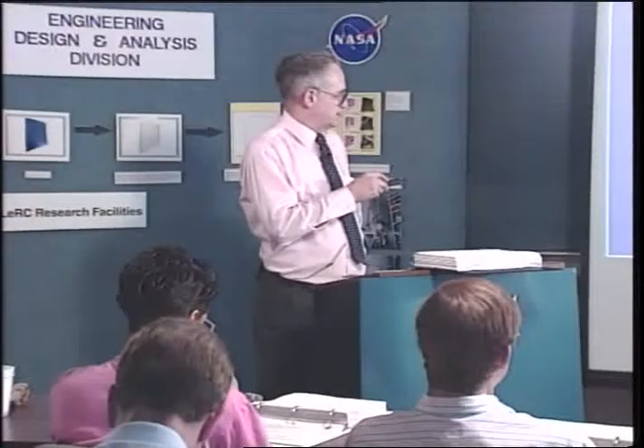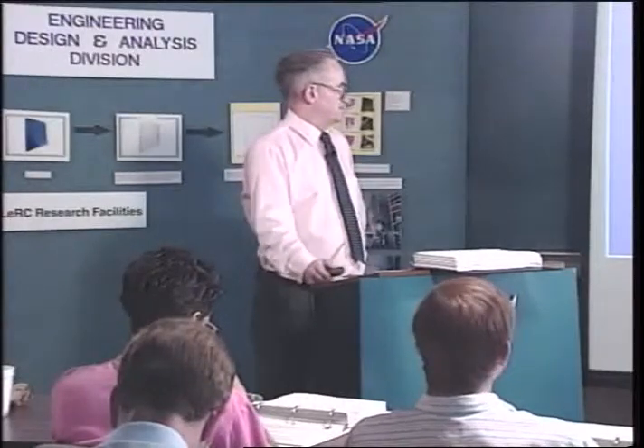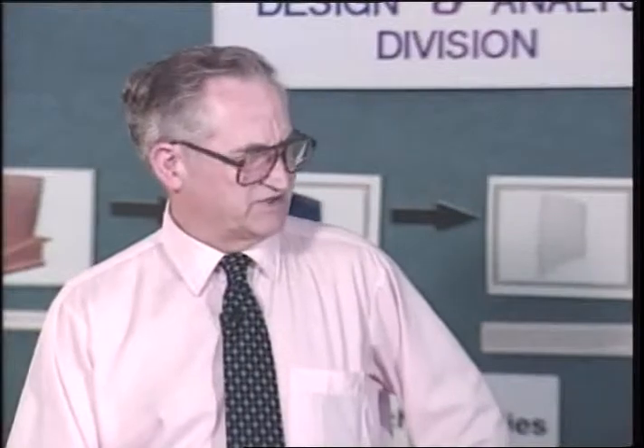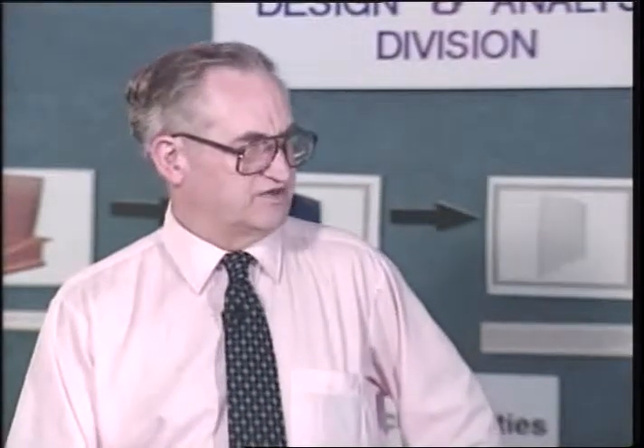Tool marks, nicks, and gouges are permitted on the under-head surface, but notice the restriction: as long as your micro-inch surface roughness does not go under 125. A 125 is really not too rough - it's a rough machining surface. The other place you would look at: if the head is banged up a little bit and it's on the corners out of the way, you could probably accept it as long as the plating surface is not gouged.